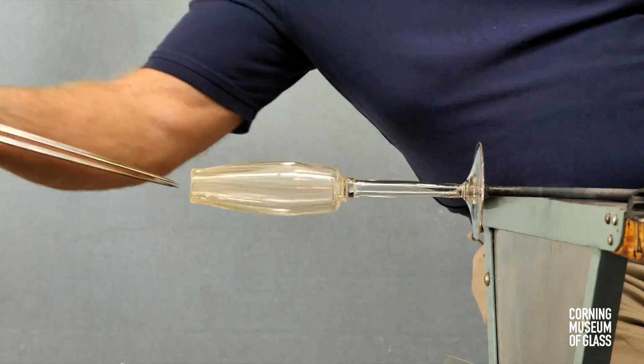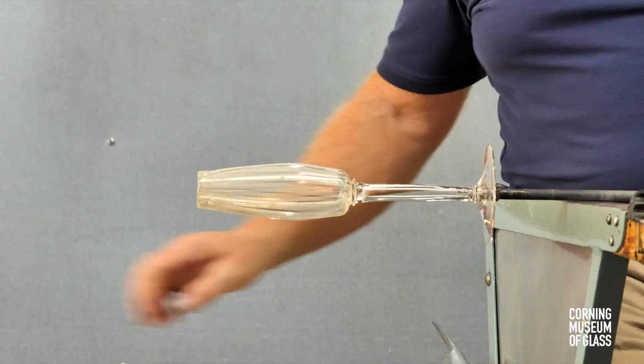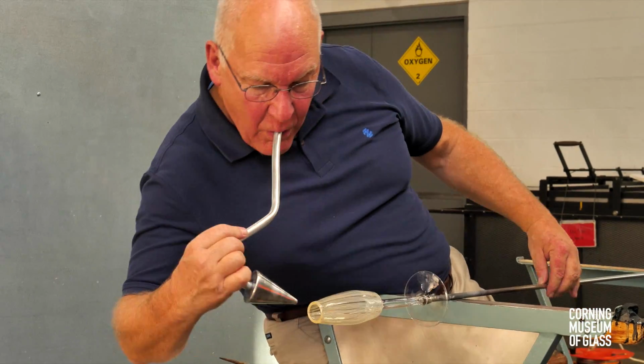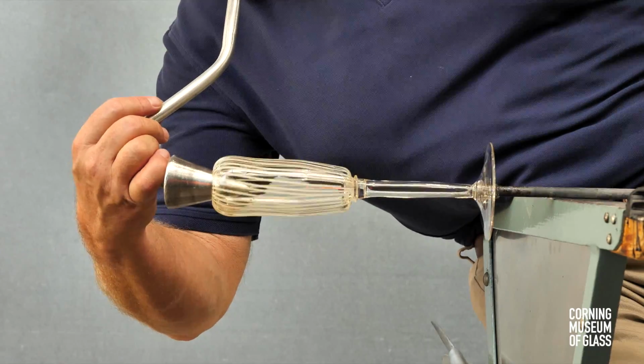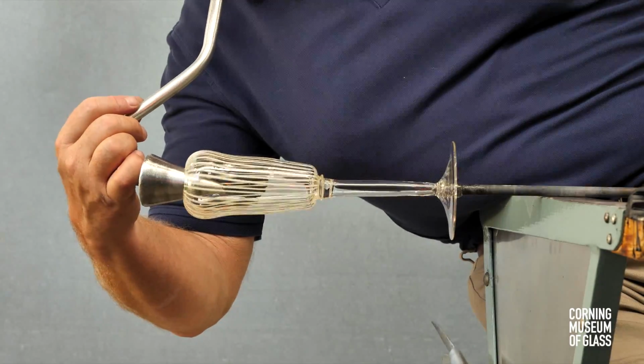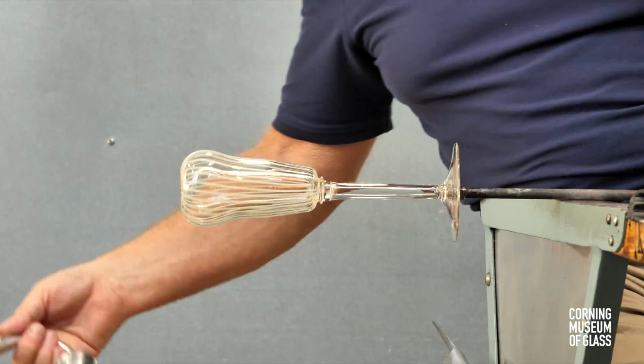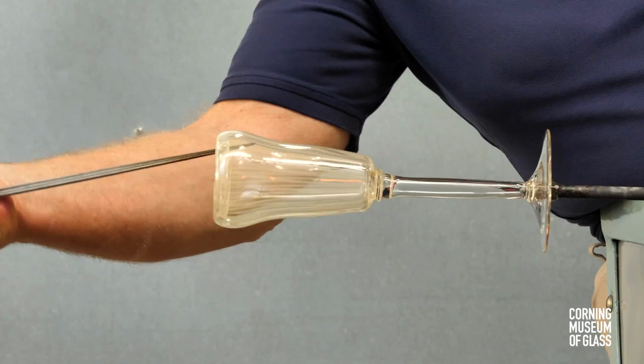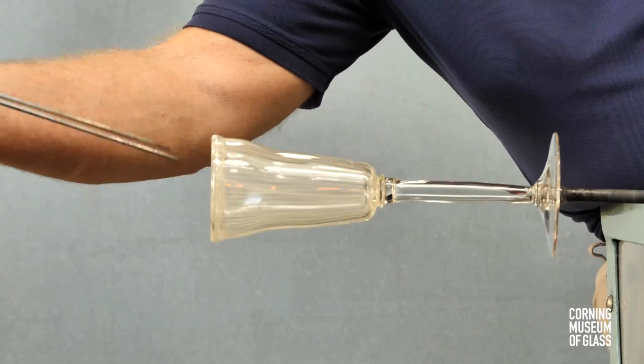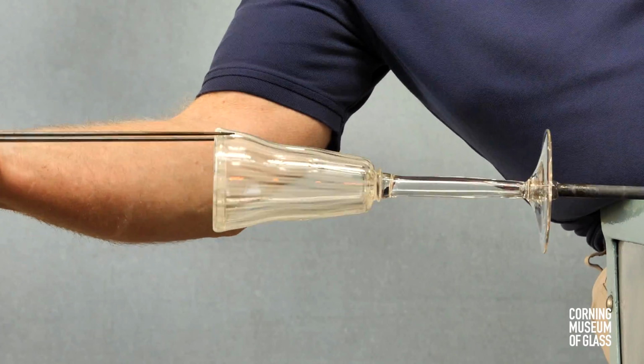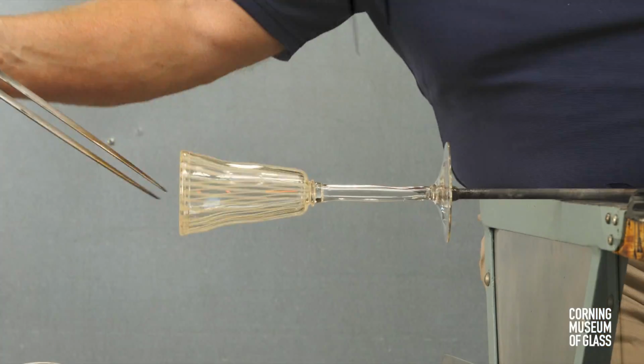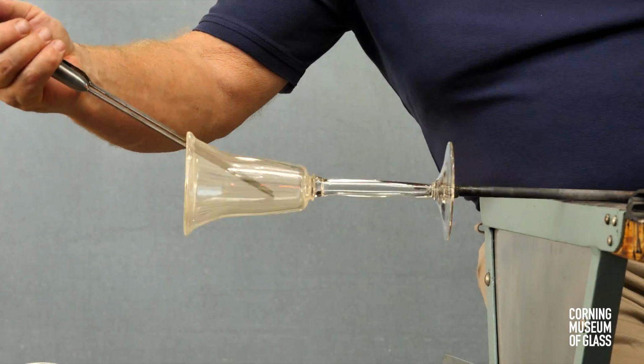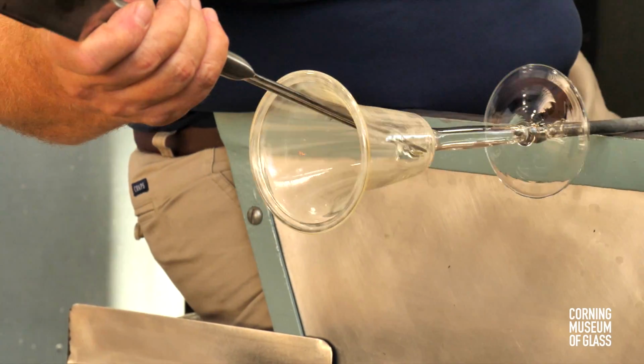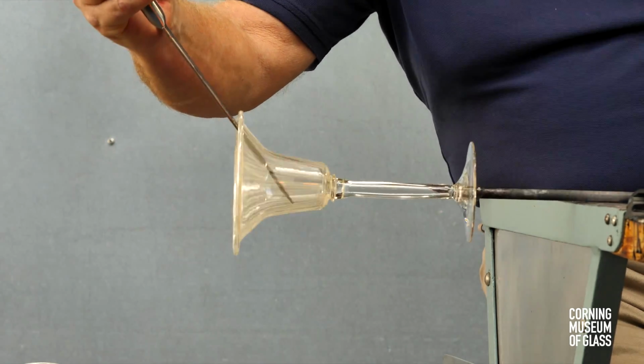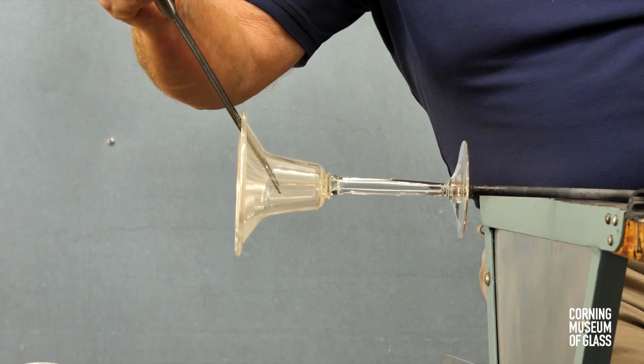After reheating, the hole is opened to the diameter of about 1 inch. The soffietta is used to cool the lower portion of the cup. The upper portion inflates. The vessel has a folded rim, so the edge is pushed inward just prior to dilating the hole. And after frequent reheats, the jacks are used to create the final flaring rim.